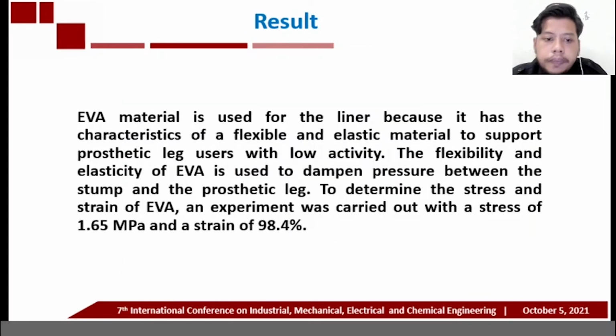The result: EVA material is used for the liner because it has the characteristic of flexible and elastic material to support prosthetic leg users with low activity. The flexibility and elasticity of EVA is used to dampen pressure between the stump and the prosthetic leg. To determine the stress and strain of EVA, an experiment was carried out, with stress of 1.65 MPa and strain of 98.4%.